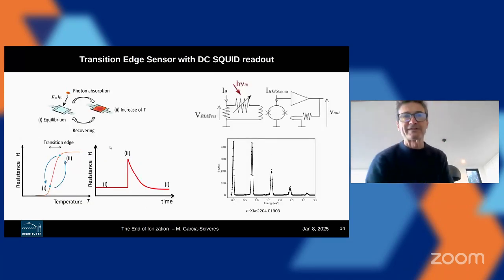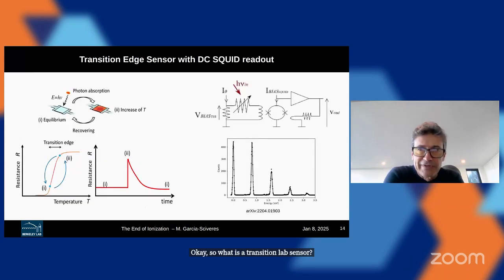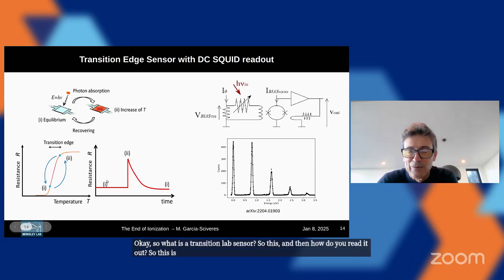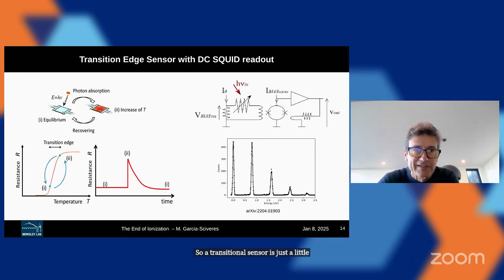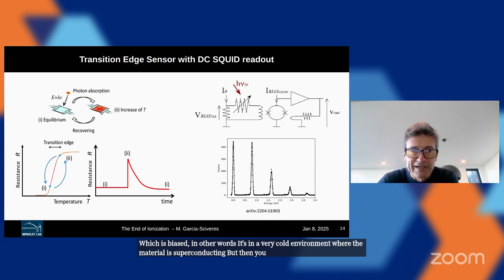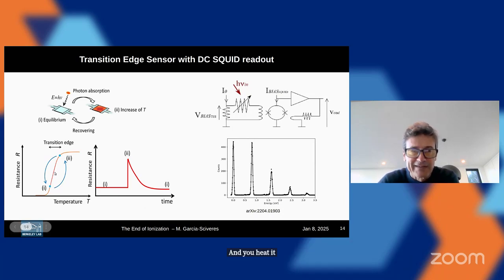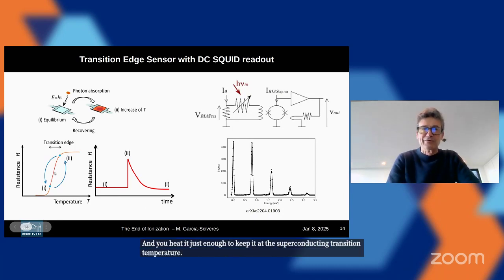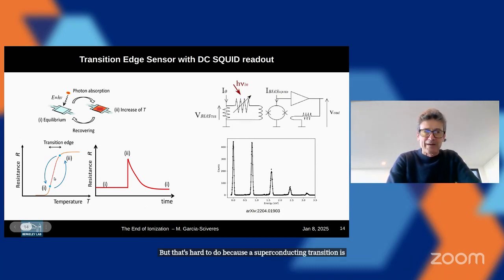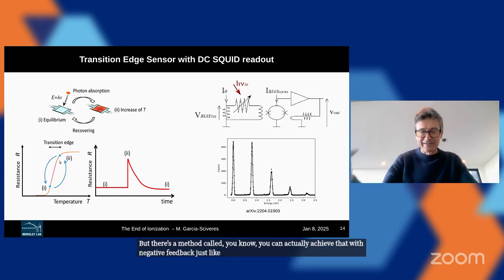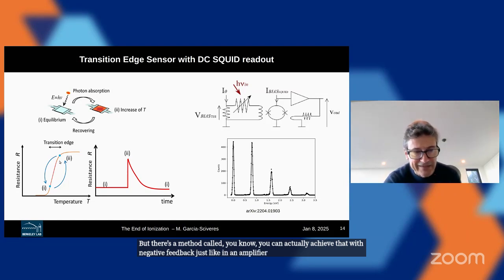Okay, so what is a transition edge sensor? And then how do you read it out? This slide is a primer of that. A transition edge sensor is just a little chunk of superconductor, which is biased. In other words, it's in a very cold environment where the material is superconducting, but then you heat the material by running a current through it, and you heat it just enough to keep it at the superconducting transition temperature. That's hard to do because a superconducting transition is very sharp. But you can actually achieve that with negative feedback, just like in an amplifier where you have an op amp with negative feedback, same kind of thing.